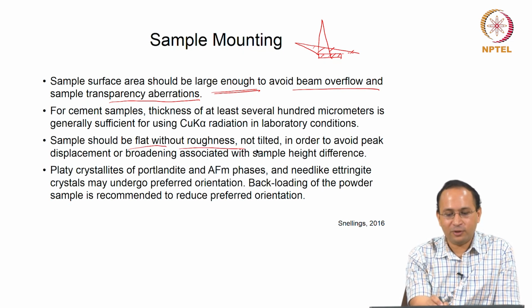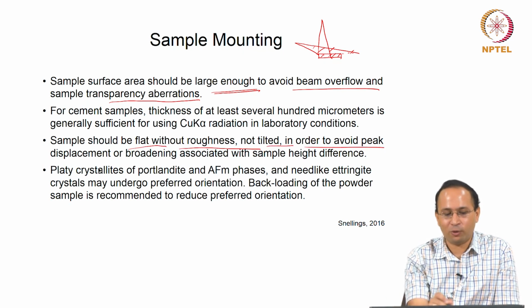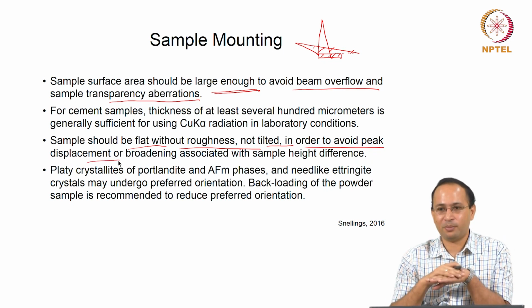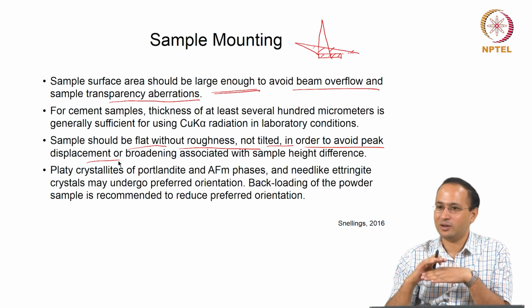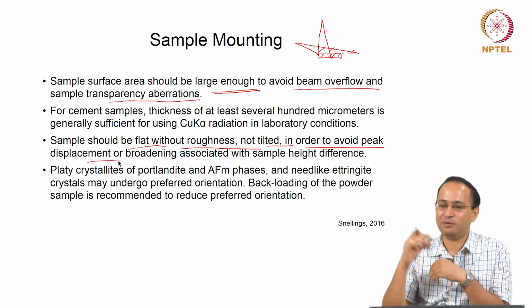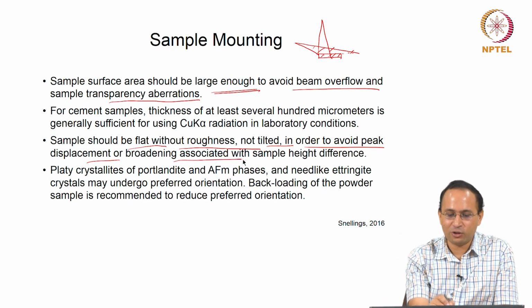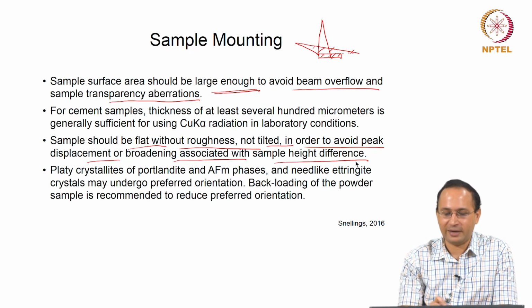The sample should be flat without roughness, not tilted, in order to avoid peak displacement. You have to make sure your sample is flat, without roughness and not tilted, because that will again affect your peak displacement. We talked about it. If it is not in focus, then you will see peak displacement, and you may also have broadening associated with the sample height difference.